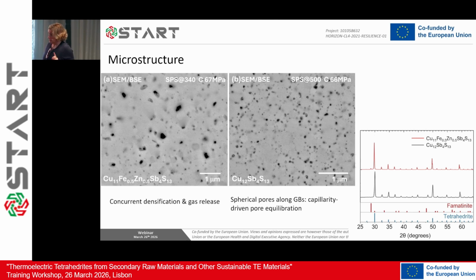One important aspect about tetrahedrite is that the mean phonon free path is about the atomic distances, meaning that what is important is the rattling of the copper atoms. So if you put nanoprecipitates or pores, they're never going to be efficient in dispersing heat transport phonons. This is documented in the literature, there are papers about this for tetrahedrite. So in principle this would be a bad thing, but these tetrahedrites have quite high ZT values, above 1. So we still don't know, we need to study this further.